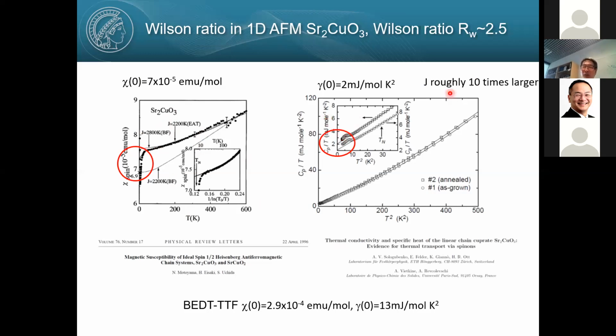And since the bandwidth of the spinon band is roughly scaled by J, and those copper oxides have almost 10 times larger J bandwidth. Okay, and the density of states is scaled by 1 over bandwidth. So therefore, they have much smaller chi and gamma compared with the organic case, but that's consistent with much larger J. So they are smaller, but if you take a ratio of the T equals 0 limit susceptibility and gamma, we get the Wilson ratio of 2.5, slightly larger than 1.5, but of the order of 1.